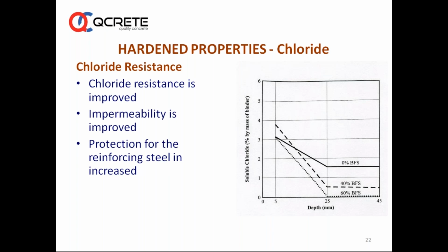So this is another slide which shows that at a depth of, for example, 25 mm, the chloride is at about 1.75% when you are using no GGBS or fly ash. But when we use about 60% GGBS, the chlorides are almost nil at about 25 mm. When the depth touches 25 mm, there is no availability of chlorides. So you can see from this graph the resistance to chlorides is significant, and this is one of the best ways of making the concrete durable in an environment where more chlorides are available. Next.